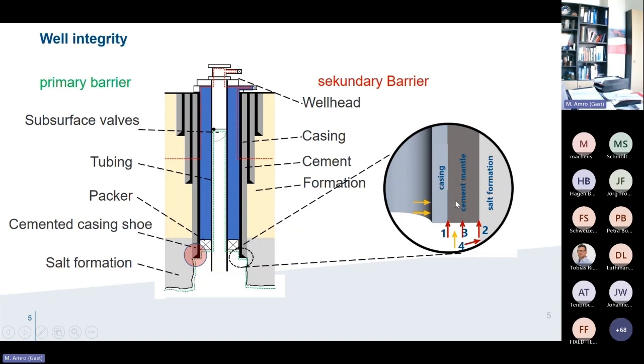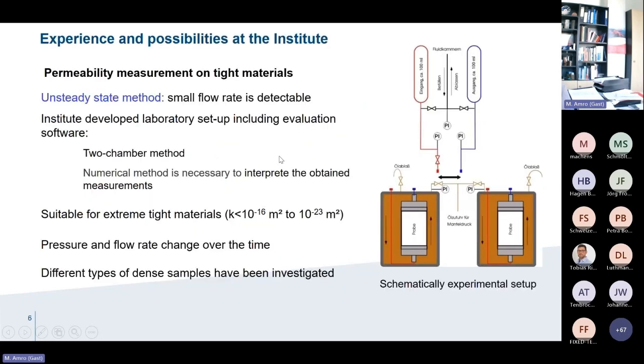Yeah? And I tried to make it here schematically. We have the casing here, we have the cement, then we have to investigate the interface between casing and cement, and the cement itself. And we have to consider also the cement and salt in this particular case, because we deal with salt caverns, and we have to consider the salt formation itself. That means we have to see the applicability of the salt for hydrogen. So if we want to deal with the leakage or with the flow within the system, that means we have to identify the permeability, which is very important.